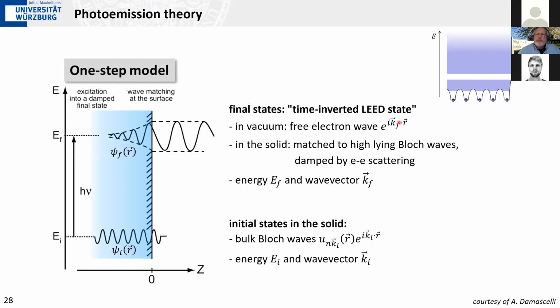In vacuum, these waves are just free electron waves, which have a certain momentum, Kf, which may or may not be different from the initial state momentum. And then we have to match it to the high-lying Bloch states that we have in our solid, and also have to take into account this damping due to the electron-electron scattering appearing here in the solid. And what we measure then is this final state energy and the wave vector of our photoelectrons. So this has to be viewed as one single coherent process,